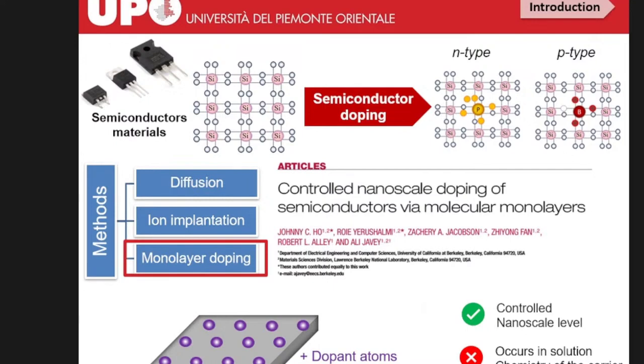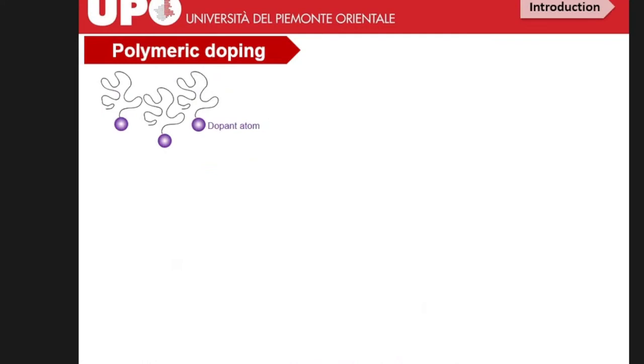But it occurs in solution, and this is not a good situation for industrial applications. And if I want to modulate the amount of the dopant atoms on the surface of the semiconductor, I need to change the molecule. If I change the molecule, I will change the chemistry of the reaction. So again, this is not useful for industry. So our idea is to use polymers, because in this case, we don't have to change the chemistry of the molecules, but we can just modulate the molecular weight of the polymer and use the same chemistry.